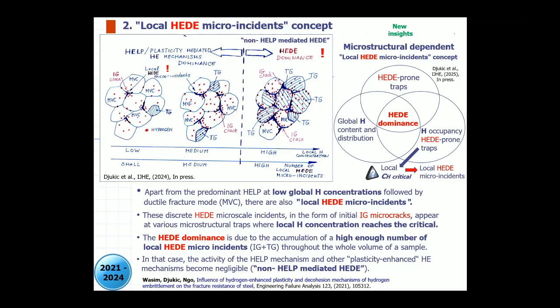And it depends on three factors. This is still work in progress. It depends on the global and local hydrogen concentration of the material, and particularly the distribution of hydrogen, whether it's localized in some area. Also, we have particular microstructural features which are prone to HEDE and some which are not prone. One example: you have a precipitation strengthening alloy, and one type of precipitate, when it saturates with hydrogen, is prone to HEDE. Another type of precipitate in the same alloy is not prone to HEDE. So they can accumulate a much larger hydrogen content and not produce the drop of ductility due to decohesion.